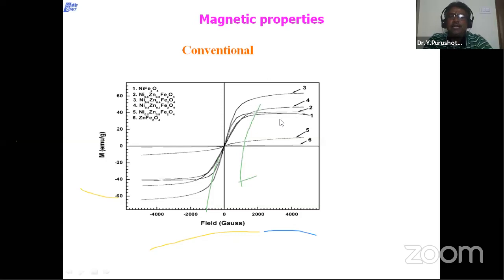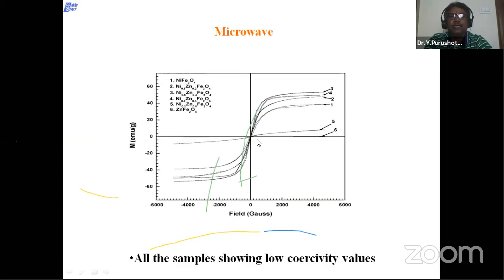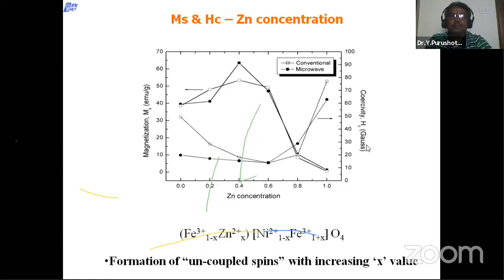And since these are all soft magnetic materials, coercivity will be less only. These are the micrographs and BH loops, the hysteresis loops of the conventional and microwave sintered materials. Both types of materials are showing low coercivity only because these are soft ferrites. And saturation magnetization and coercivity versus zinc concentration has been plotted. This is because of formation of uncoupled spins with increasing X value, so the coercivity has a low value.